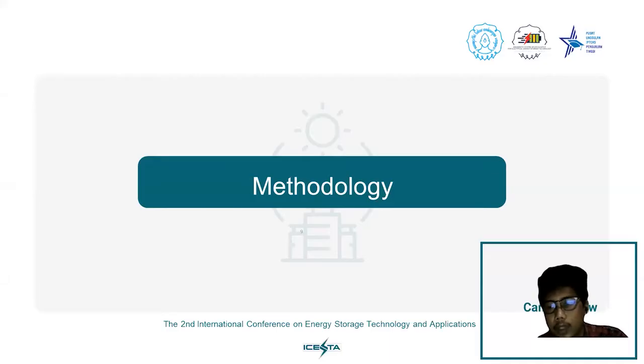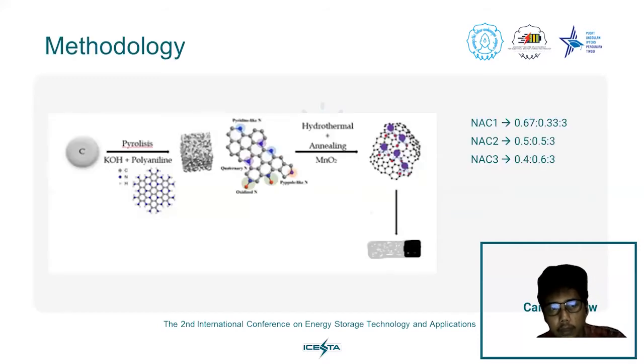Okay, thank you, Eric. Now we go to methodology. For the methodology, we use a pyrolysis process for activating carbon. So the carbon from coconut shell that we got, we impregnated with potassium hydroxide and polyaniline for the nitrogen precursor. For the composition ratio, you can see here for NaC1, NaC2, and NaC3. After that, we mix it with MnO2, and process it with hydrothermal and annealing process.